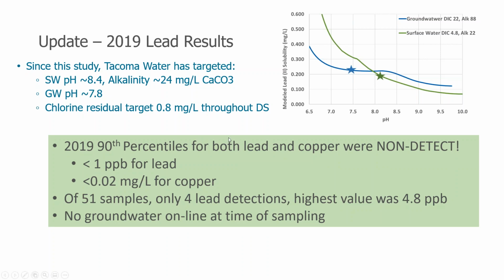That means their 90th percentile was less than 1 part per billion for lead. And of the 51 samples, only 4 had detections. The highest detected value was 4.8. Now, once again, because of operations, there was no groundwater on at the time of sampling, but I think the city can be rest assured that they've optimized the treatment between targeting the pH and chlorine for the DIC of their groundwater, so that levels will be as low as they can go, and they're truly optimized.